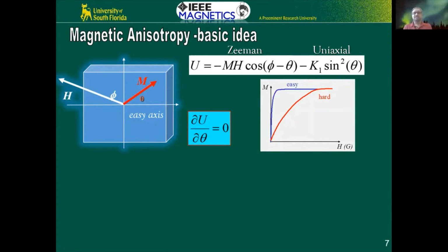So in this case, it's a very simple term, K1. It's a uniaxial term because, guess what? Nanoparticles typically are spherical, and you really don't have a preferred direction. So that's what we use in terms of a simple way to represent the anisotropy energy. So that's uniaxial anisotropy. So as you can see, it's a competition between the Zeeman term and the internal energy, or the anisotropy energy, in any given magnetic material.